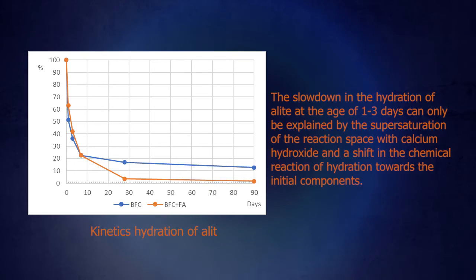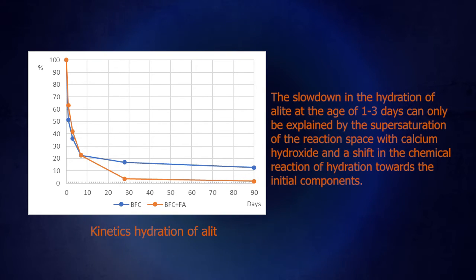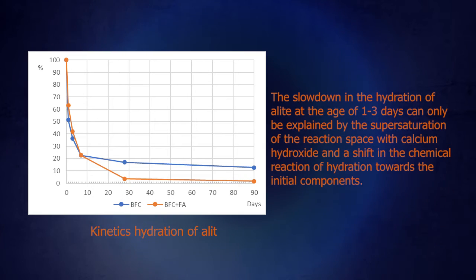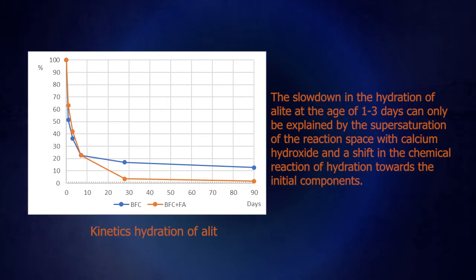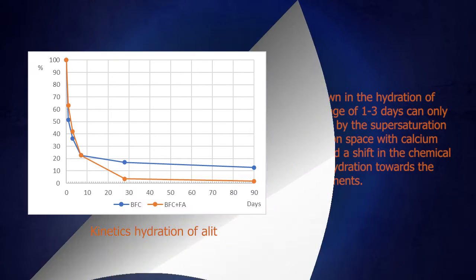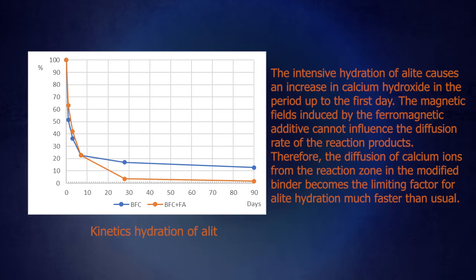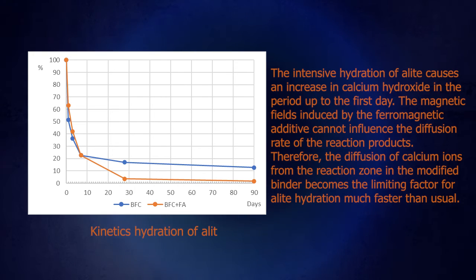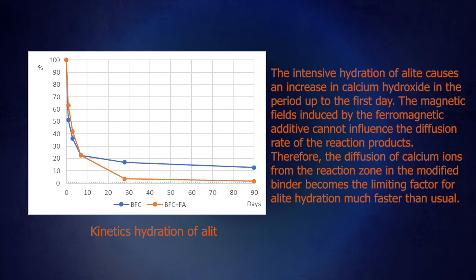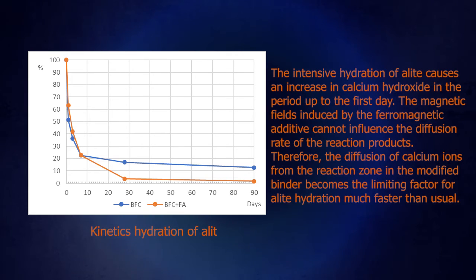The slowdown in hydration of alite at the age of 1 to 3 days can only be explained by supersaturation of the reaction space with calcium hydroxide and a shift in the chemical reaction of hydration toward the initial components. The intensive hydration of alite causes an increase in calcium hydroxide in the period up to the first day. The magnetic fields induced by the ferromagnetic additive cannot influence the diffusion rate of the reaction products.